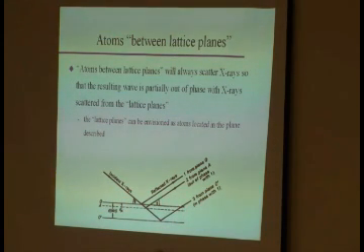Here's one of your planes. Here's your next plane spaced d_hkl apart. And there is this atom A that is sitting at a distance d_A from the original plane. Now, as long as all the atoms scatter X-rays, atoms on this plane and on that plane will scatter in phase, which means the path difference will be equal to a multiple of lambda, right?